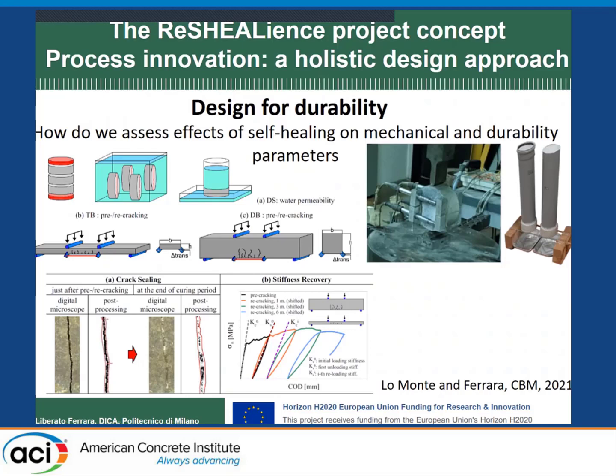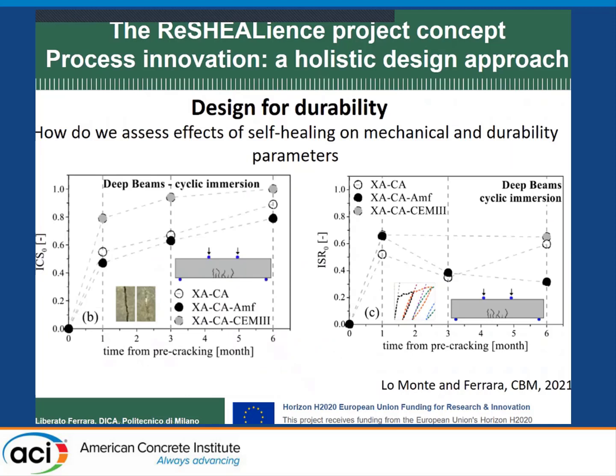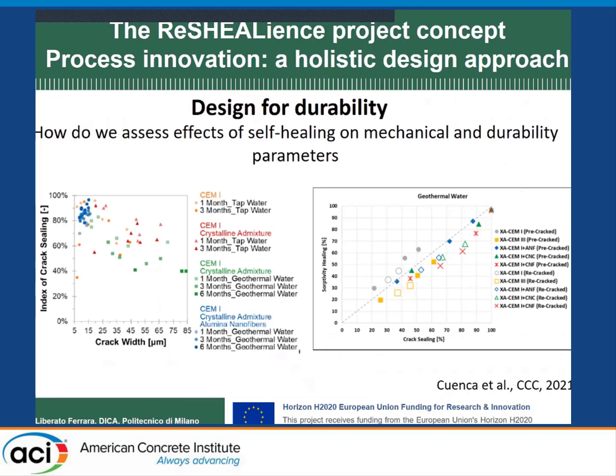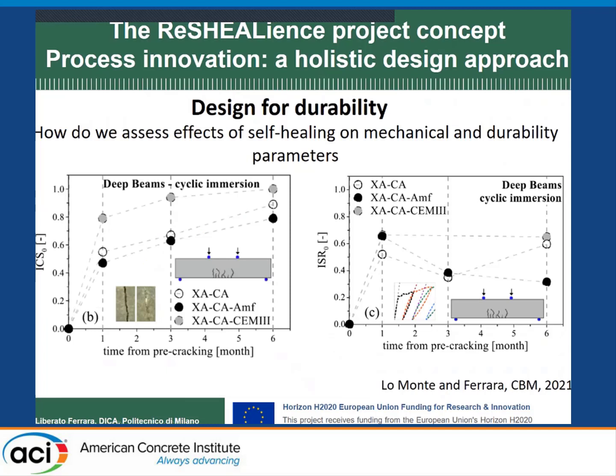And we evaluated, for example, this is crack sealing, the crack closure. So you can see that over a long time, up to 6 months, you go up to 80 or 90% of crack closure. And also the recovery of stiffness, which is on the graph on the right, well, it's less performant, but you can still reach about 40 to 60% recovery of the stiffness, which actually turns into recovery of damage.